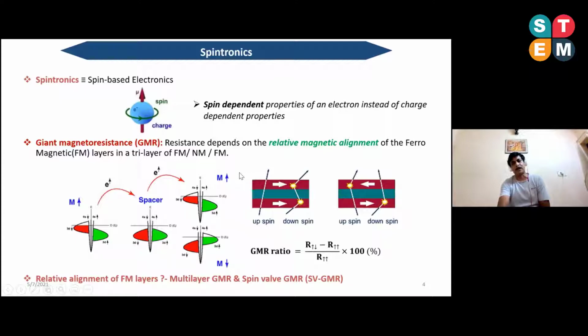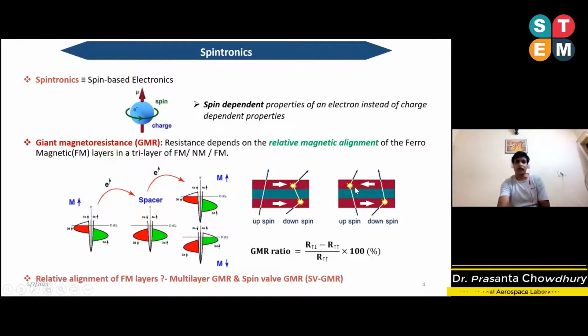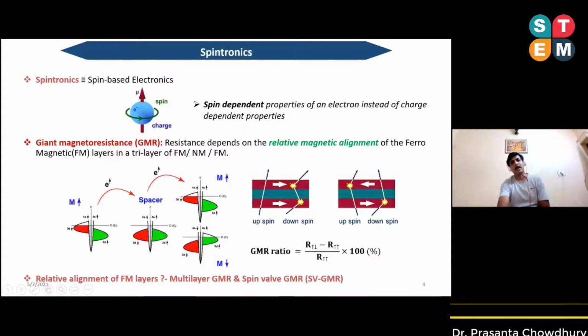As we know very well with GMR, if you have two magnetic materials separated by a spacer layer, like copper, then depending on the spin alignment, whether both spins are parallel or anti-parallel, the polarized spins traveling through give a minimum resistance. And when they are in anti-parallel configuration, both minority and majority spins get scattered by the two different layers, and we get a higher resistance.